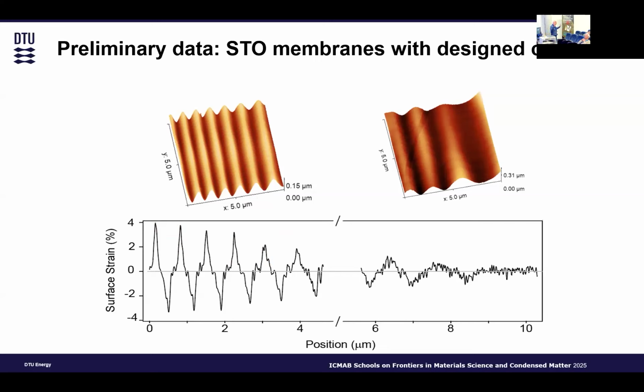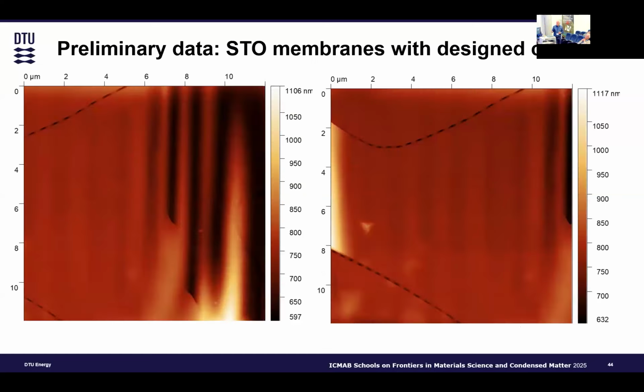I cannot show you results, so I disappoint you already now. We are currently working on measuring with the PFM, and we believe that at 4% we should be able to see some results. The fact is that we can tune it. This is interesting. So this is a normal sinus curve, and this is a decaying sinus. So we can change the amplitude, we can change the wavelength, we can change the material as we wish.